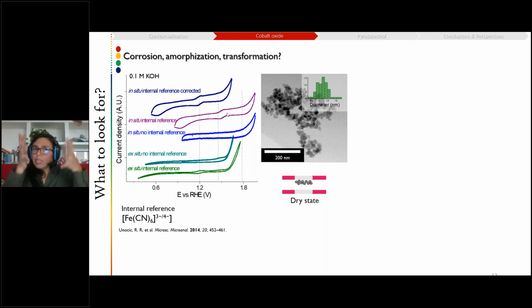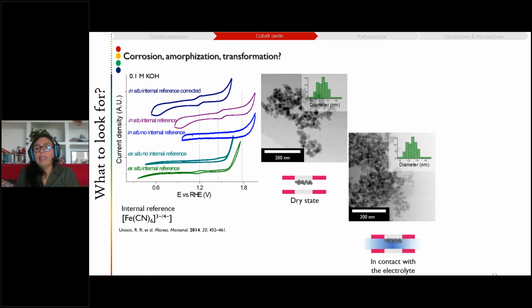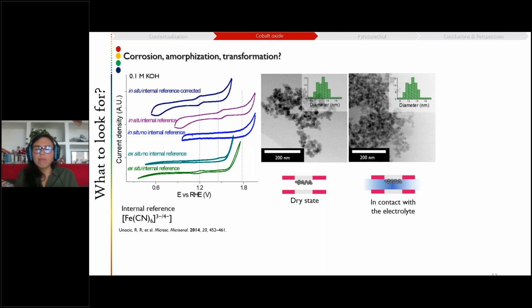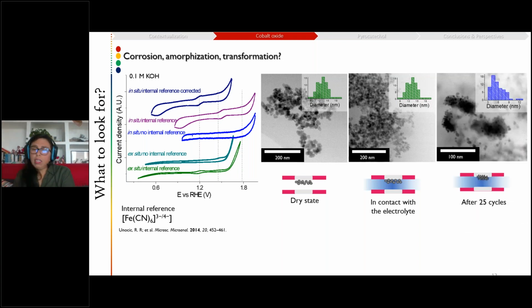Once we are sure that we are working in the potential range that we wanted, we can start our experiments. The first thing that we could do was to observe our materials in a dry state, meaning only deposited over the electrode. The nanoparticles had a size between 12 and 15 nanometers, more or less. The first thing our system allows us is to see if the interaction between the particles and the electrolyte induces any immediate changes, so to say. We didn't observe any changes, at least in terms of the general morphology and the size of the nanoparticles. So the electrolyte doesn't change the nanoparticles significantly.